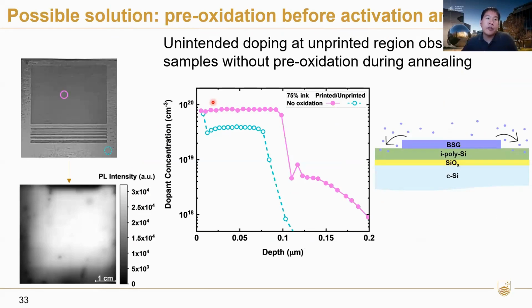So what can we do? We are exploring some options now, and one of them is doing a short pre-oxidation just before the 950 degrees activation anneal. This image here is roughly what our printed image looks like. There's a solid area and then lines, and the areas around it are not printed.